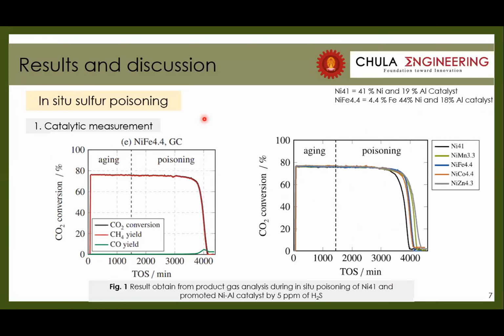The results and discussion of in situ sulfur poisoning: measurement of catalytic deactivation and hydrogen sulfide poisoning at 400 degrees Celsius. This figure shows carbon dioxide conversion after aging. The carbon dioxide conversion is divided into three states. In state one, hydrogen sulfide is adsorbed at the front end of the hotspot, causing deactivation in this area. But carbon dioxide conversion stays constant because the non-poisoned fraction of the fixed bed reactor still reaches equilibrium.